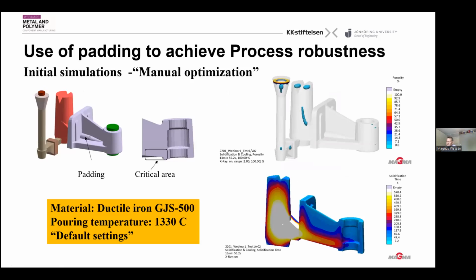In the first case, to make this work, the foundry had designed some gating system, a feeder, and they couldn't find a way to remove the porosity in this very critical area. They had to add some padding material, and hopefully the designer or the casting buyer could accept this padding material to create directional solidification. This is what you have to do. So the target of this manual optimization was to add some material so that you could get the directional solidification all the way from the feeder into the part, so that you have good feeding and you can avoid the porosity. And this is what was achieved.